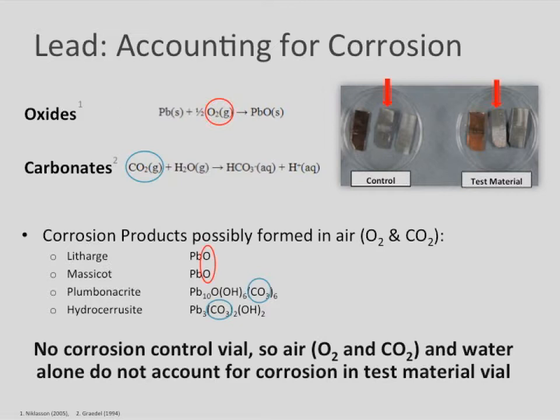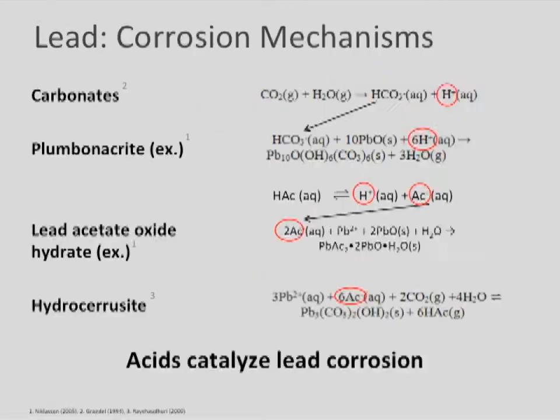So what is it in the preservation material that is providing the bump it needs to form these corrosion products, and does that matter for our collections? You can see the oxides would be formed—litharge and massicot—with oxygen, and these carbonates obviously need carbon dioxide. But we don't see those in large quantities on the control. So what mechanisms are forming these corrosion products?